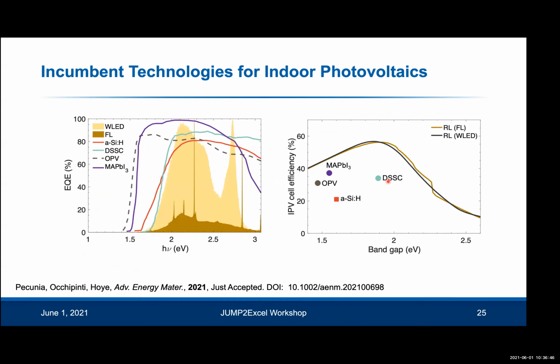And this is the area in which crystalline silicon doesn't work so well, because crystalline silicon dominates the outdoor market because it's efficient and cheap. But indoors, the efficiency drops quite a lot because at a low level of illumination, the dark current dominates compared to the light current, and that substantially reduces the efficiencies. Because of that, amorphous silicon has gained more traction in the industry, but even that isn't really that efficient. At best, it's 20% efficient indoors, but most devices are less than 10% efficient.